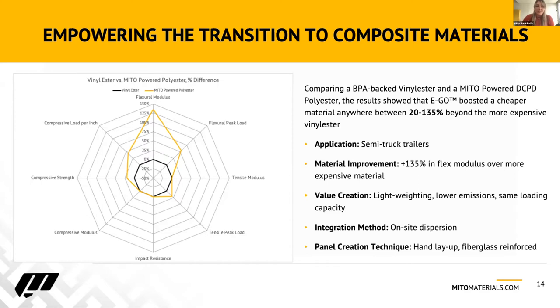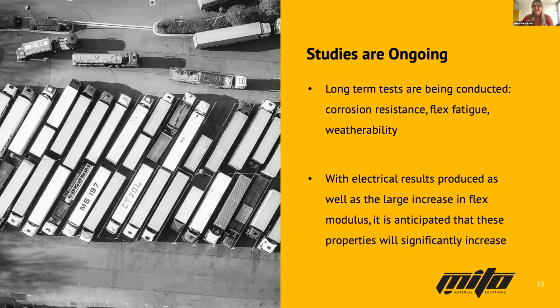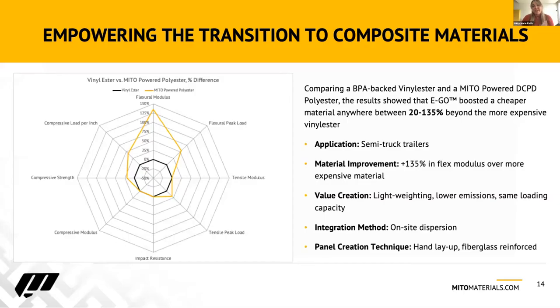We see also improvements in compressive load per inch, flexural peak load, and overall compressive strength and tensile peak load, leading to a longer estimated fatigue life. So this was using chopped fiber mats and polyester resin systems. And we are continuing these studies using the hand layup and fiberglass reinforced systems that they were looking at too.